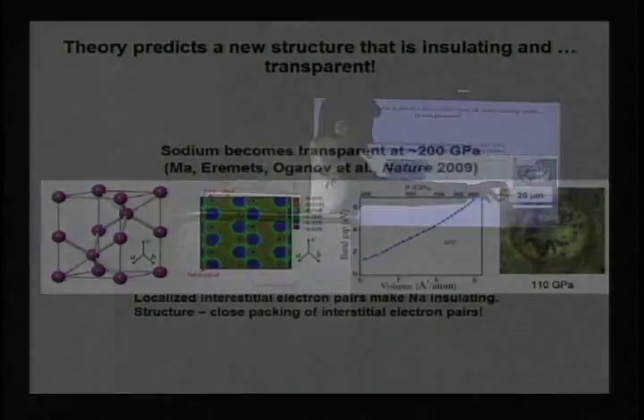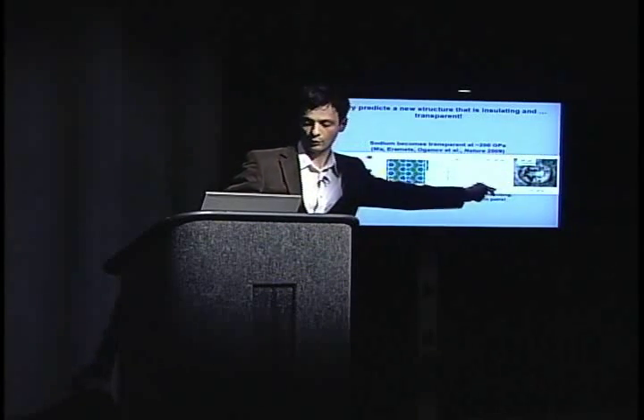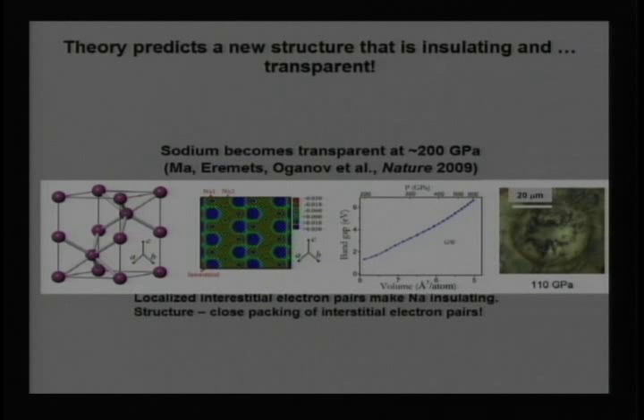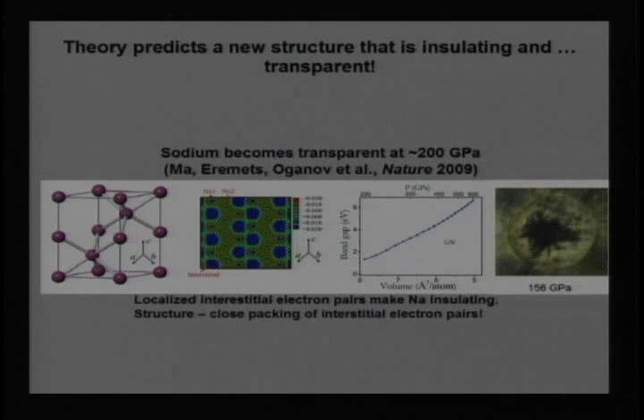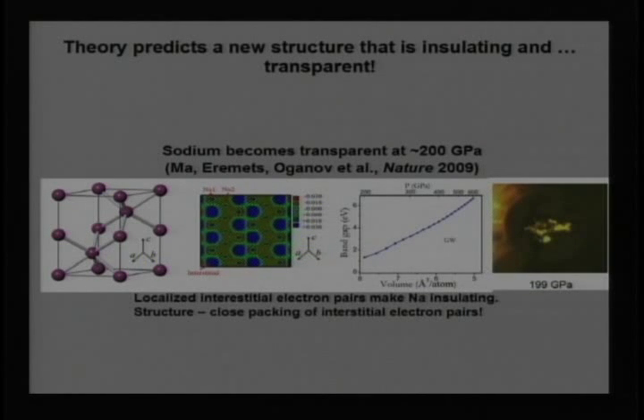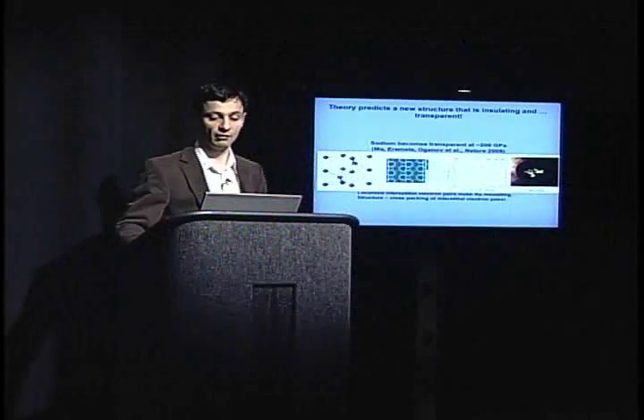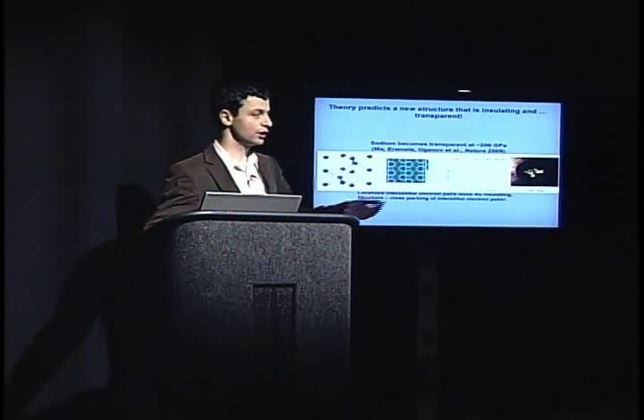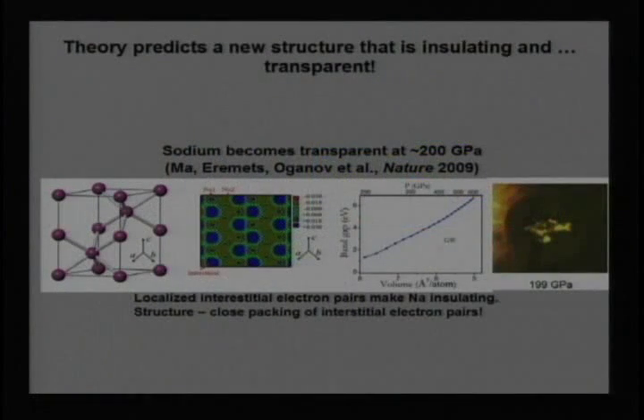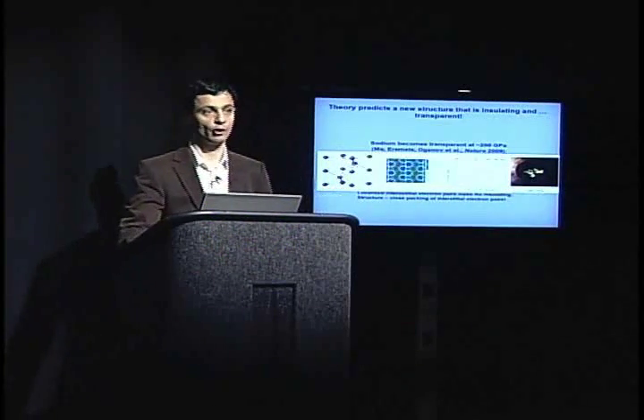Let us look here. This is what sodium looks like at pressures of up to slightly more than 1 million atmospheres, or 100 gigapascals. It's a white, silvery, shiny metal. If you increase pressure to 1.5 million atmospheres, it transforms into a black, non-reflecting material, which is either a poor metal or even a semiconductor. We increase pressure further, and indeed, at 2 million atmospheres, sodium becomes transparent, reddish in color, and as you decrease pressure, you revert back to a white, shiny metal. So this magical experiment that we conceived in our minds was realized by Eremets in Germany, and indeed it proves that our predictions were correct.